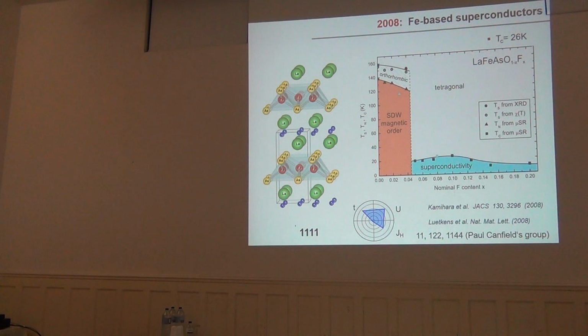And how are the structures of these materials? These are similar structures to the cuprate. These are layered materials, iron, arsenic. Here I'm showing this so-called 1111, iron arsenic, separated in this case by lanthanum oxygen planes. And basically by doping the system, I'm also changing the charge in these planes, and I can then get mobile charges that go into the superconductivity.